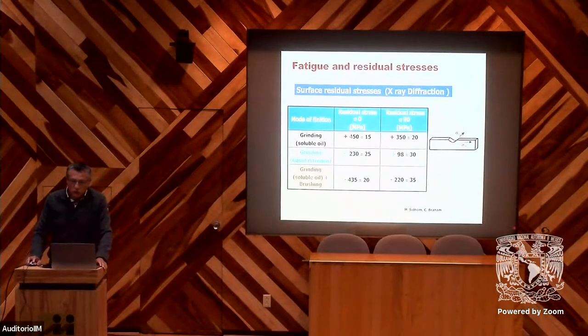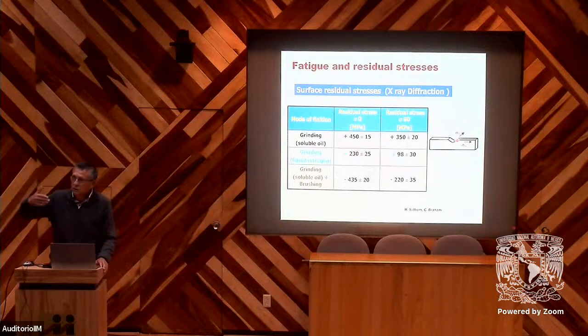So if we consider this on fatigue tests, for example, here we consider the stainless steel 316L tested in fatigue. This is the Wöhler curve. For a ground surface, we can observe that if we compare this state to an electropolished surface, that means after removal of the layer affected by the machining, we have an improvement. That means we have a reduction of the fatigue life by grinding. This is attributed to the presence of high tensile residual stresses in the two directions, the machining direction and the transverse direction.